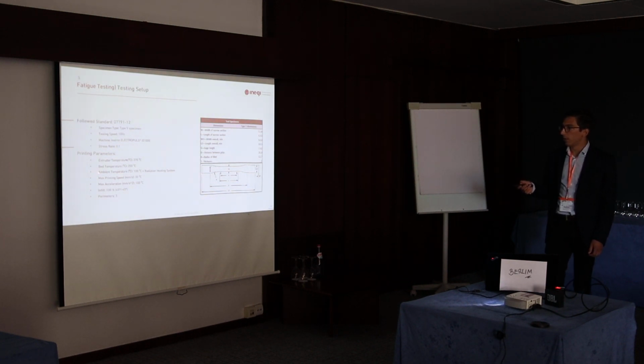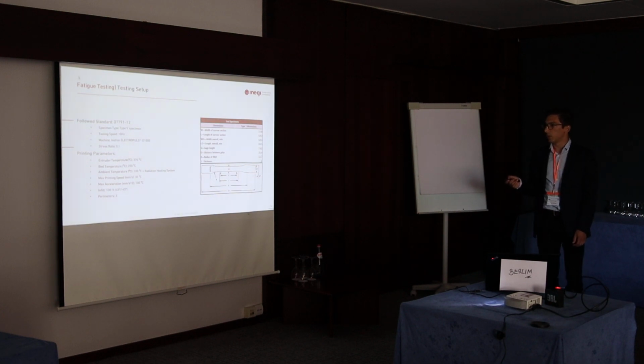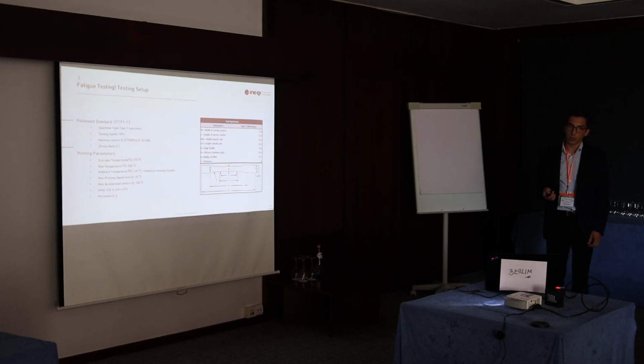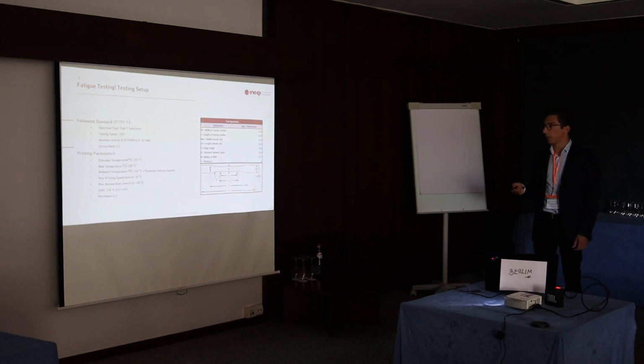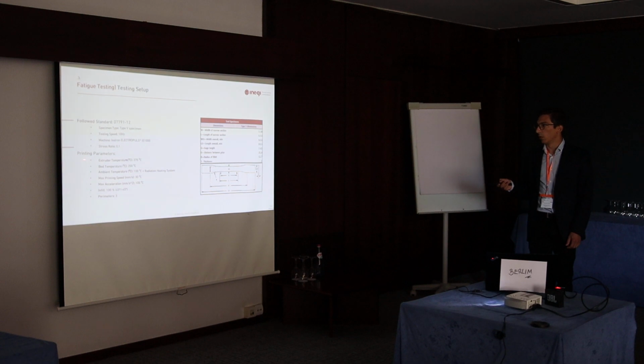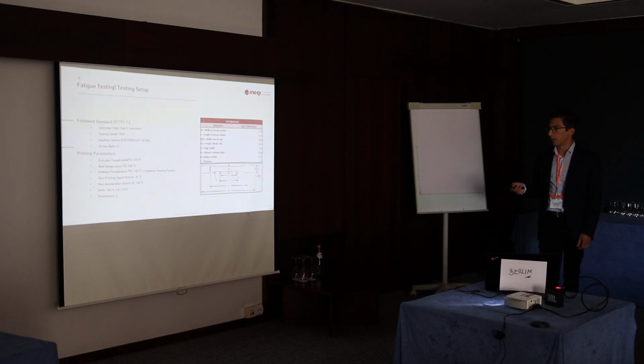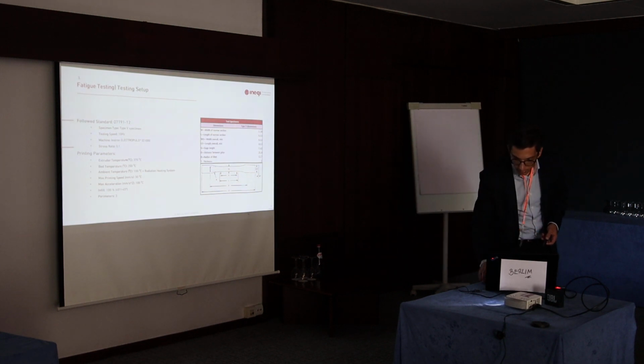For this fatigue testing, the printing parameters chosen were 370, which is kind of in the middle of the range specified by the manufacturer of the material, so we believe it to be the most common printing parameter. And then we kept all the rest as for the tensile testing.